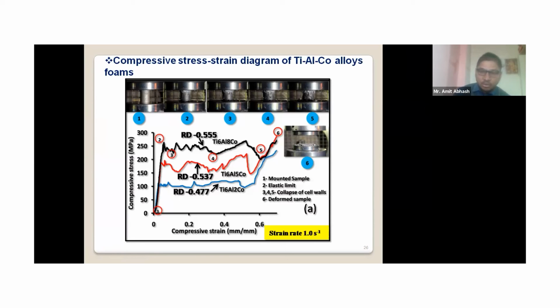But since this is an open cell foam that we are discussing here, we see some fluctuation in the diagram. Maybe there is a sudden collapse of the foam, then due to interlocking between the cell walls the strength increases, and again decreases. So this random collapsing of the foam mainly causes this type of stress strain diagram. Now, in the elastic region, the load unload curve: if you load or unload it, the slope of that curve gives you the elastic modulus of the material.